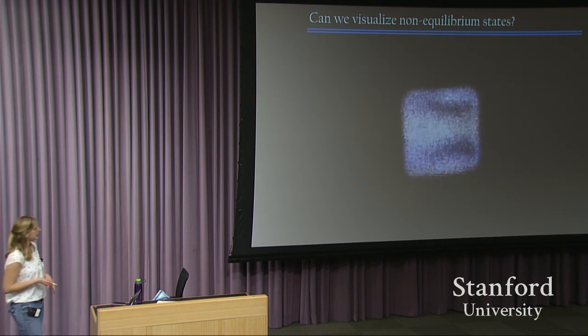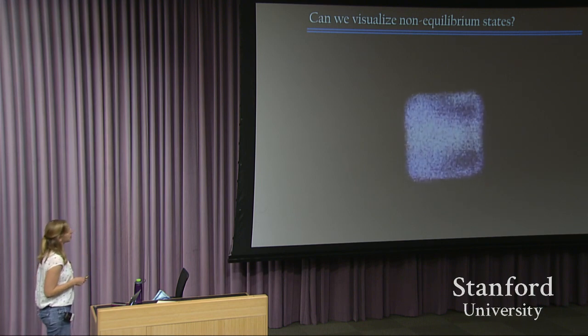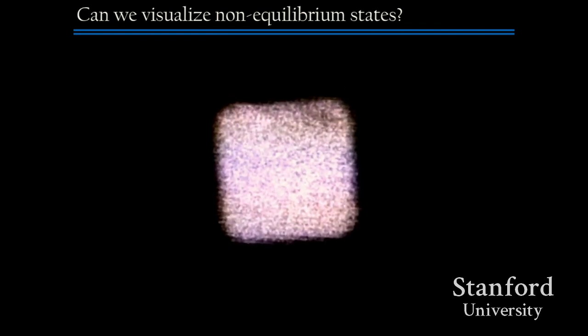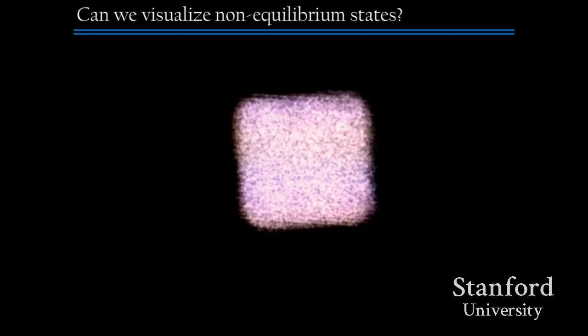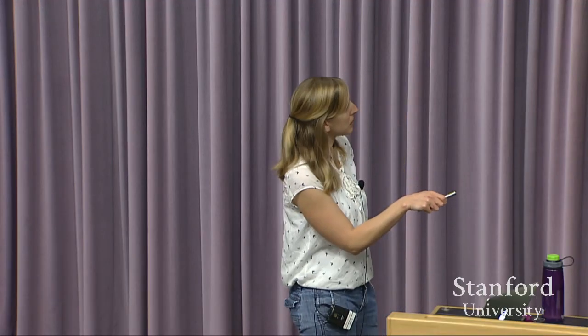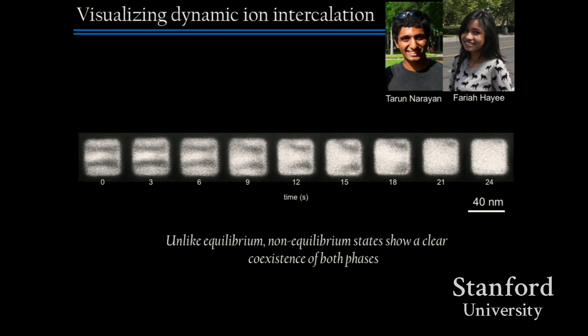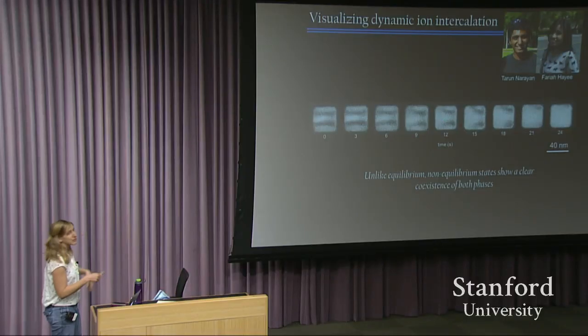So again, we're in STEM mode, scanning transmission electron microscopy mode, and we're taking advantage of both the different electronic or EELS scattering spectra plus the different diffraction patterns of the two phases. So white here corresponds to the beta phase, black corresponds to the alpha phase, and hopefully you saw this triangular front move across the nanoparticle as it transitioned from this stripy phase into the pure beta phase. So here we started off with the nanoparticle and a coexistence between alpha and beta. So we're fixed at a set hydrogen pressure. And then there's this diagonal phase front that moves in from the corners and eventually takes over the entire particle when it becomes beta.